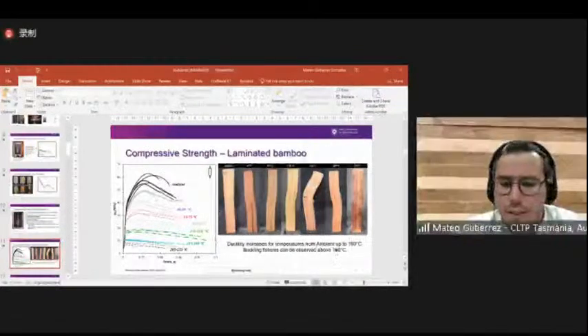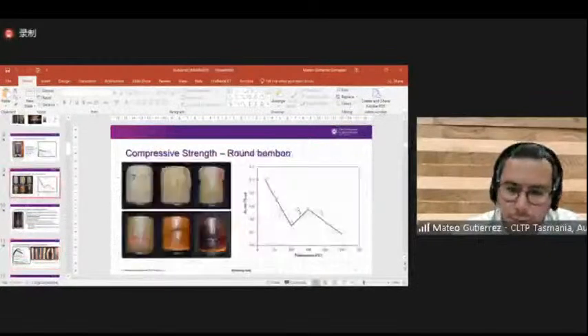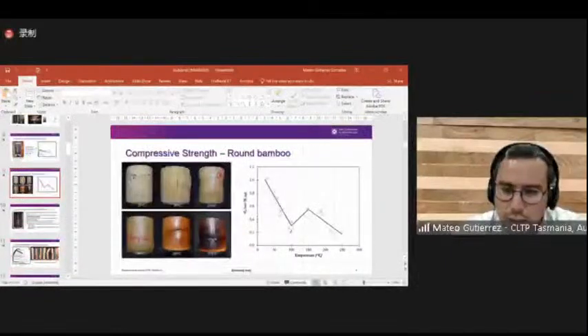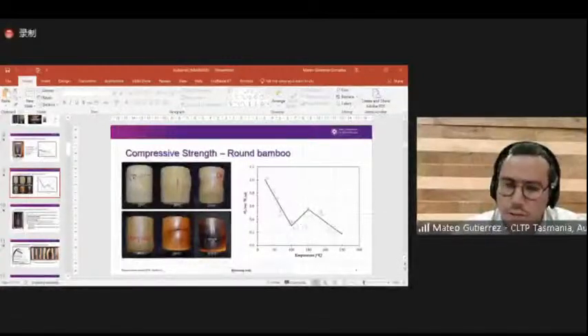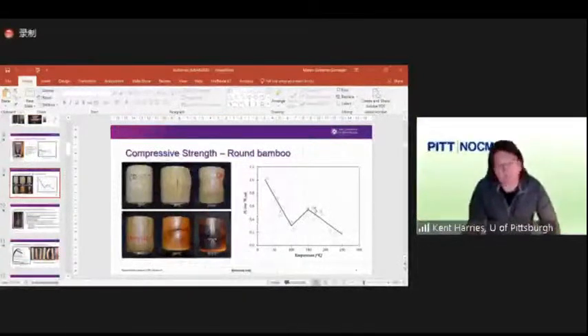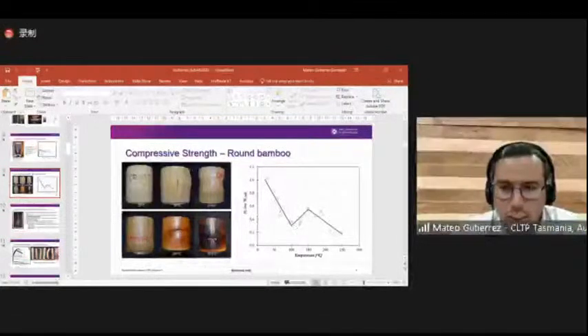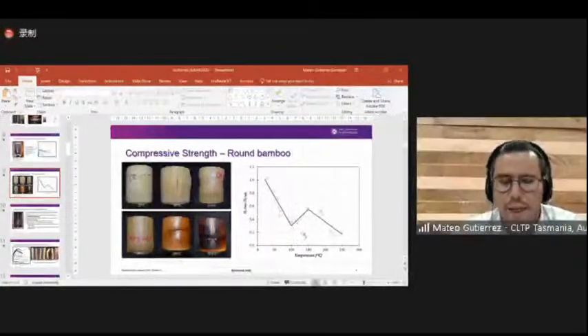It's hard to say because I didn't test different densities, so I didn't do a comprehensive analysis on density. Moisture content, definitely, because if you look at this curve here, you see that after 100 degrees there is an increase of strength, and this increase of strength is normally associated with the moisture content of the material. So there is definitely an influence of the moisture content, but I cannot say anything about densities.